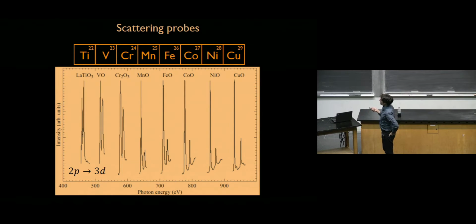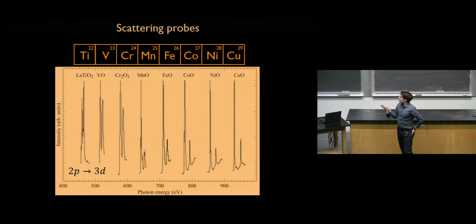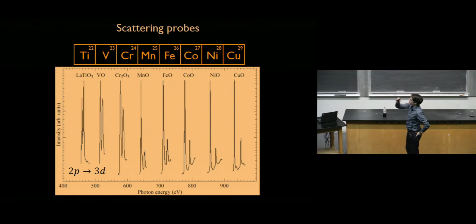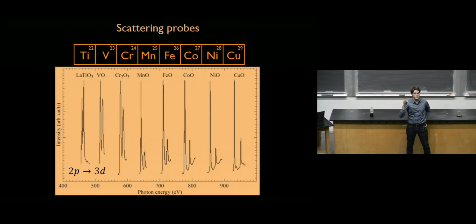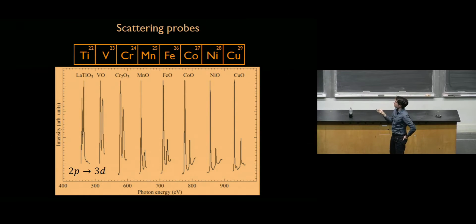So we play a trick. We go to certain resonances. So we change the photon energy of the X-rays. And at certain special energies, you increase the sensitivity to certain electronic final states that correspond to certain transitions from core level to valence electrons in materials. And they all have different energies.